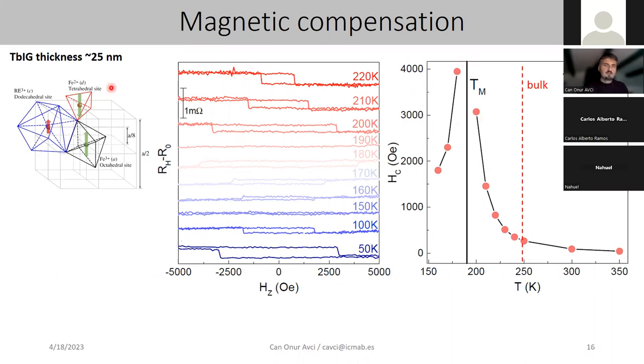In the specific film that we studied here, we saw that the magnetic compensation occurs slightly below 200 Kelvin. This was a surprising result to us because we thought that we were growing stoichiometric, perfectly bulk-like films. But it's not the case, because in the bulk, the compensation should occur at 250 Kelvin, but we are somewhat 50 Kelvin off the bulk.